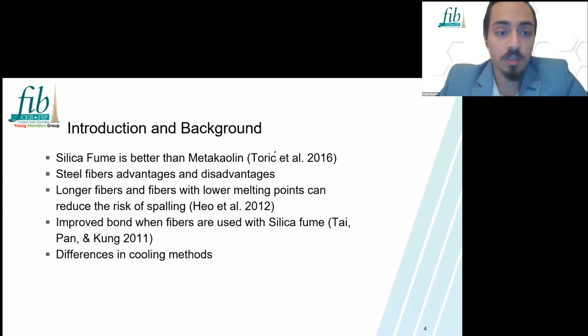Now, in terms of steel fibers, it was clear from the literature that there were advantages and disadvantages. The advantages could be, for example, enhanced bond, enhanced crack control, and clearly enhanced flexural strength. However, at higher temperatures, the fibers will elongate and will in turn create large internal stresses within the concrete, damaging the concrete from the inside, causing spalling. It will increase the risk of spalling. However, the lower melting point can reduce the risk of spalling. We will touch on that later on.